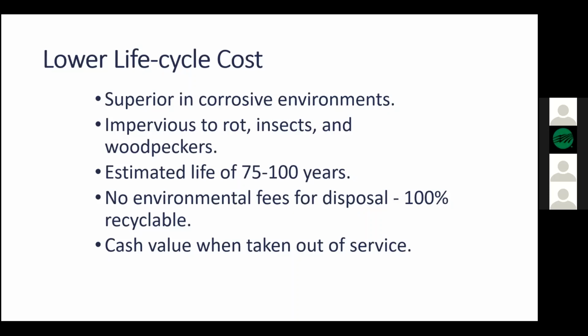Expected service life: we've only been making ductile iron poles since 2008, but we estimate the lifespan to be anywhere from 75 to 100 years. That's based on our experience with some of the other products we make, like iron pipe and iron valves. And it could be longer. We just thought that was a good number from a marketing standpoint. And typically that's going to be 2-3 times as long as many wood poles.